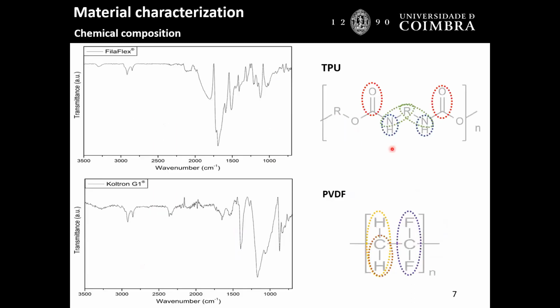So as usual, because we don't rely very much on what they say, sorry, we made some basic characterizations of the filaments. The first of all was the FTIR, just to see if we have the main chemical groups that are supposed to be in the material, and on the other hand, because we don't know if it is a polymer or a plastic, they are plastics, because at least they have the pigment additive, because no polymer is black, or blue or red or yellow or whatever. So let's see if the percentage of additives superimposes on the chemical groups of the polymers themselves, okay?